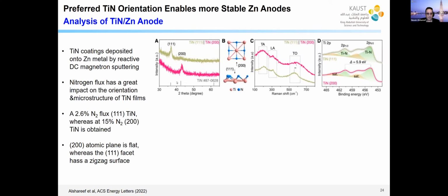It turns out, I knew this actually from background, that you can tune the orientation of the titanium nitride different ways. One of them is just to simply change the flow of nitrogen gas. And in fact, this is what happens. We have the pink here. This is a 200 oriented titanium nitride, and we have the yellow, which has mixed orientation, dominantly 111.